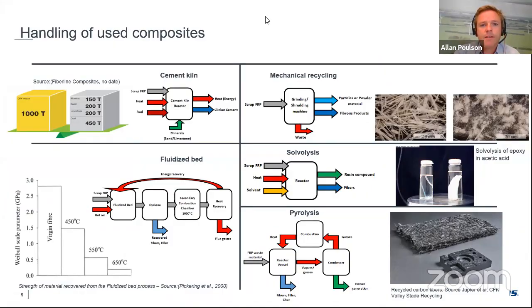Some of the processes that are available right now for recycling of composites include the cement kiln, as I mentioned before. And I think this is most likely one of the best ways of getting rid of old blades, because if you say that a blade is 50-50 glass and resin, then the glass is substituting sand that you are adding to the cement kiln anyway. That's substituting the clinker, and the resin fraction is substituting coal that you use to heat up the chemical process. So both components of the composite are used here.